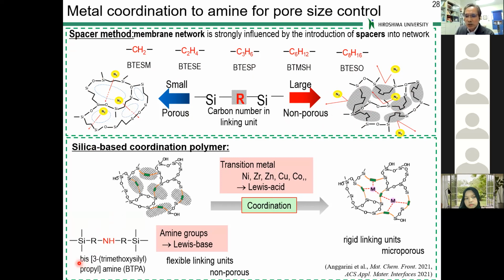She proposed to use bis[3-(trimethoxysilyl)propyl]amine, BTPA, like this. There is a secondary amine over here. With this membrane, it is non-porous due to the large linking unit. But this amine group works as a Lewis base. And then she proposed doping a metal ion, such as a transition metal like nickel, zirconium, zinc, copper, etc., as a Lewis acid. So she expected some coordination between metal and the amine groups, which gives a rigid linking unit, and then finally moves to microporous materials.